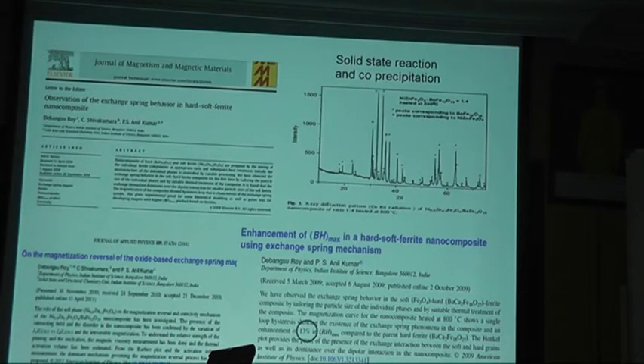For the grain size, this group gets 50 nanometer to 500 nanometer. That's not even less than 50 nanometer, but still they can enhance the properties. So I believe if we use mechanical alloying, maybe we can get better from them, hopefully, inshallah.